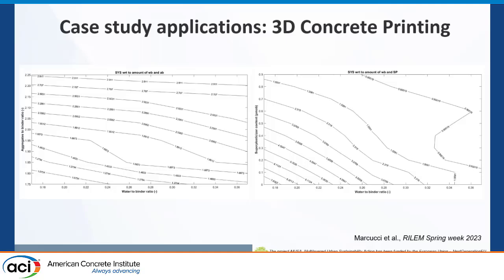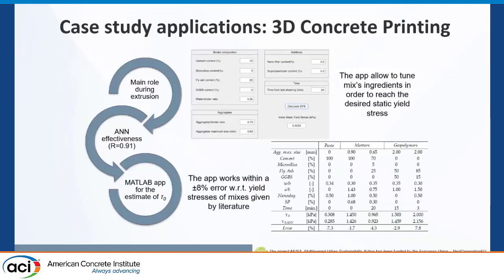So we ended up, this is published in the proceedings of the RILEM Spring Week 2023, with design cards like this, which correlate the yield stress, the static yield strength, to different mix design variables, which could be the cement content, the binder content, and the superplasticizer content. Actually, this was possible thanks to the use of neural networks and artificial intelligence, which helped us to process and to have some reliability confidence on this data.